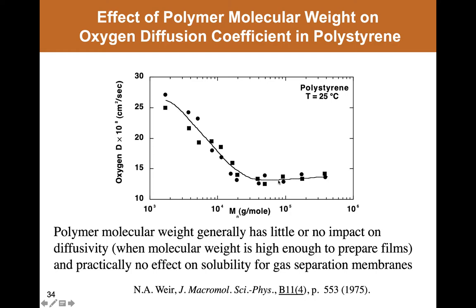And what's going on here is at low molecular weight, a polymer will have a lot of chain ends. The lower the molecular weight is, the more chain ends it has per unit volume, for example. Those chain ends tend to be more mobile than chain segments that are in the interior or middle of the polymer chain, simply because the segments of the chain that are in the middle are bound by covalent bonds to monomers on either side. And once you get out to the chain ends, they're only bound to the polymer chain on one side of that last monomer. And so the chain ends in polymers tend to be more mobile than the interior chain elements. And when you have more chain ends, then you have a more mobile matrix, and transport properties like diffusion are faster.